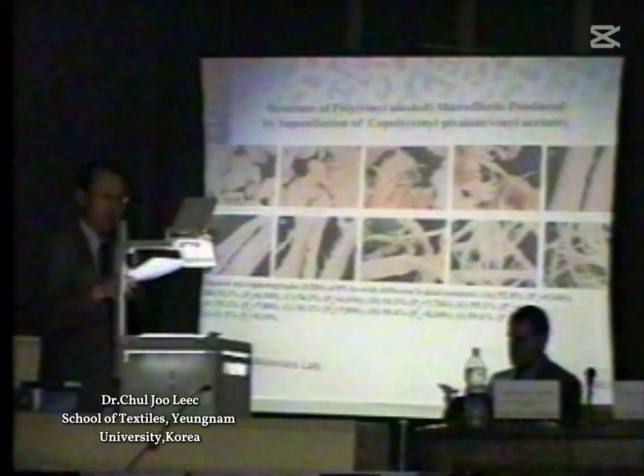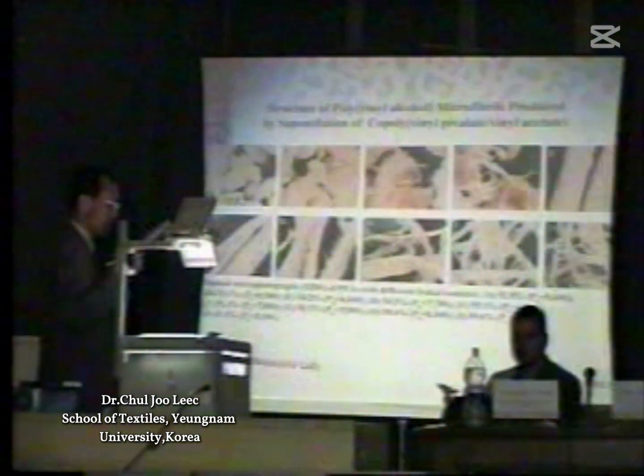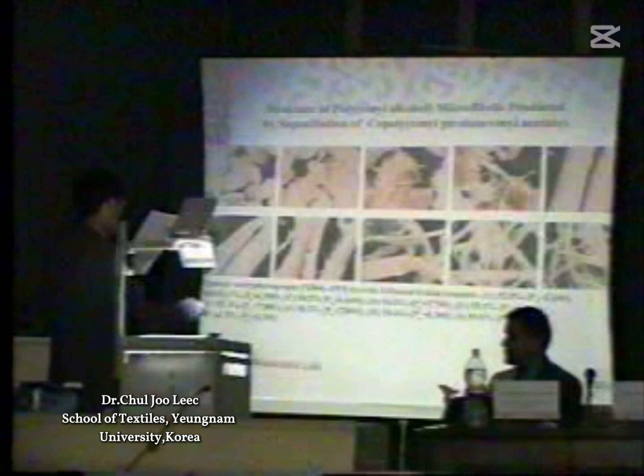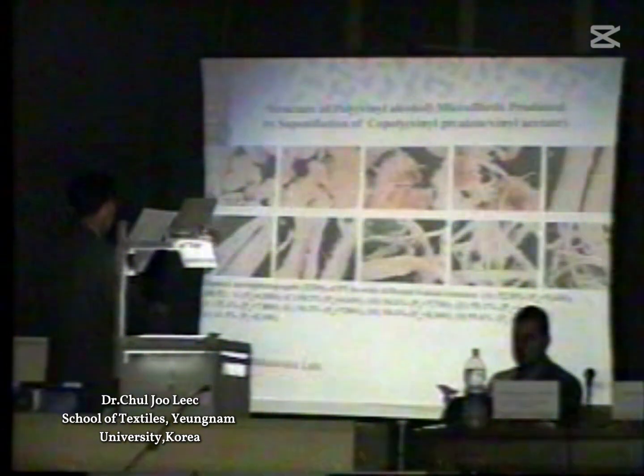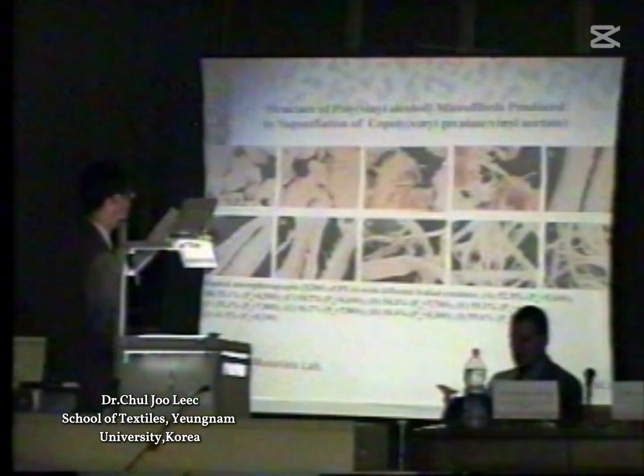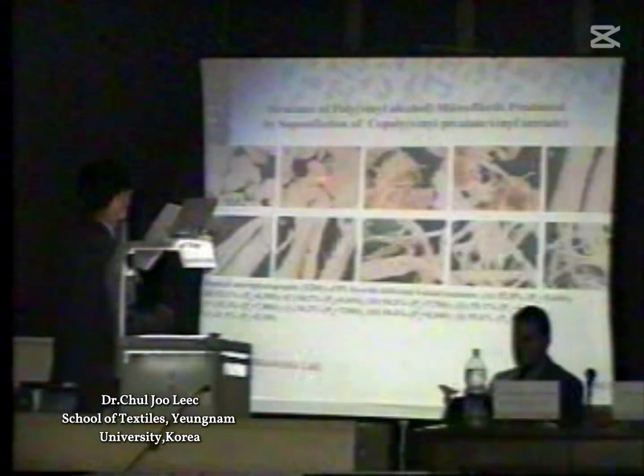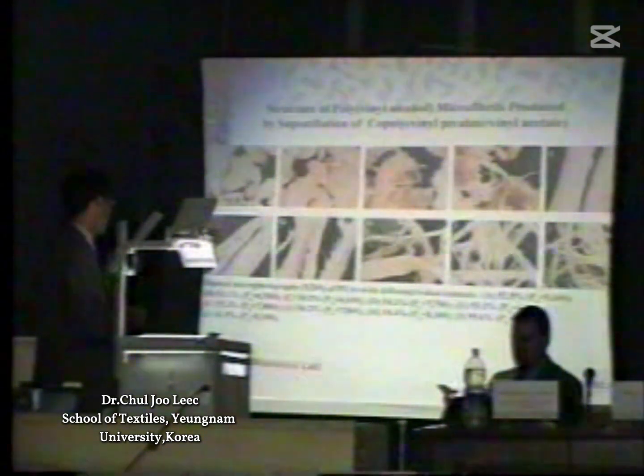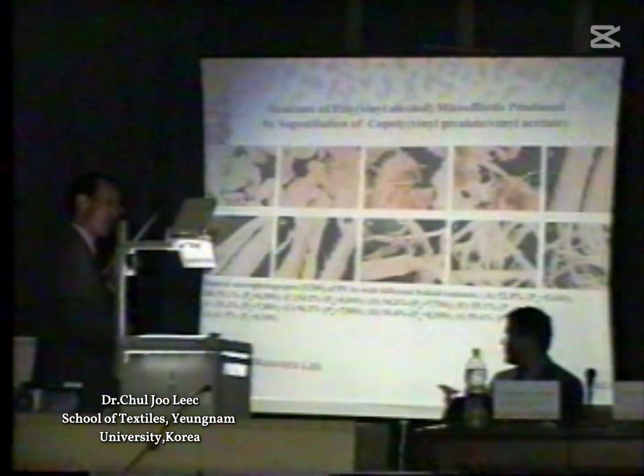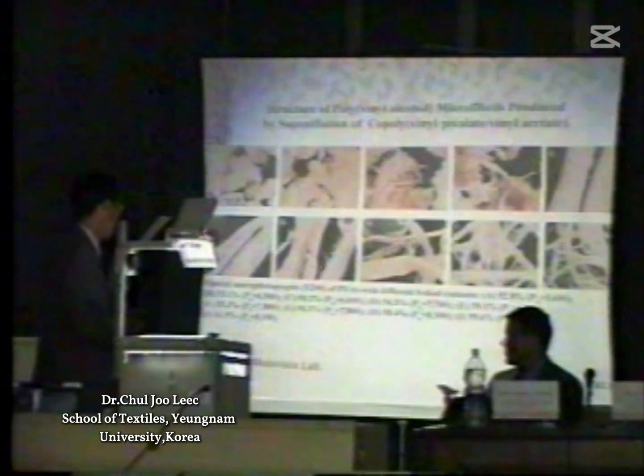Furthermore, we can see a sharp transition between 55% and 56% of syndiotactic diad content, as you can see in the pictures E, F, G. E has a syndiotactic diad content of 55.1%, F is 55.3%, and G is 56.2%. But as you see from these pictures, figure E and figure F don't have any significant evidence of fibrillars. But from figure G, whose content is over 56% syndiotactic diad, we can see the evidence of fibrillars.